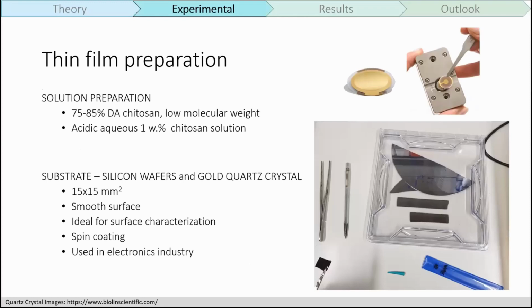Moving on to experimental work. To prepare thin films, we firstly had to prepare a solution made out of low molecular weight chitosan, dissolved in acidic aqueous solution. The solution was then deposited onto a substrate, which was either silicon wafer, which you can see in the bottom right corner, from which the 15 by 15 square millimeter substrates were cut out, or on the other hand, gold quartz crystal, which you can see in the top right corner.